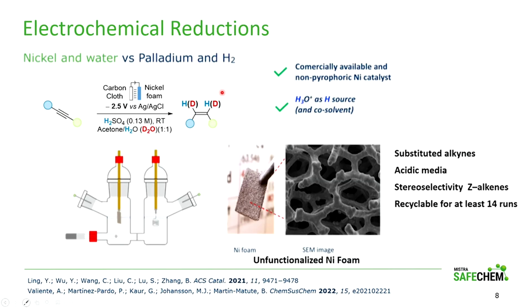So here what we have done was to replace the palladium catalyst by abundant nickel catalyst. And this is a nickel foam, and here you have a picture of it. And we have also worked on replacing dihydrogen by acidic water. So in order to use this, then we need to use also electricity. So this is an electrochemical reduction.